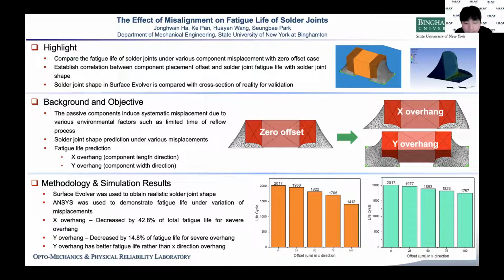For Y overhanging, fatigue life of severe overhanging is decreased by 14.8%, and the severe misaligned case in X-axis would reduce 42.8% of total fatigue life compared with zero placement offset, because the solder length rapidly decreased when the component is shifted further to the right or left direction. So therefore, the passive components overhanging in the y-axis have better fatigue life than on the x-axis. This is what I did for this work.